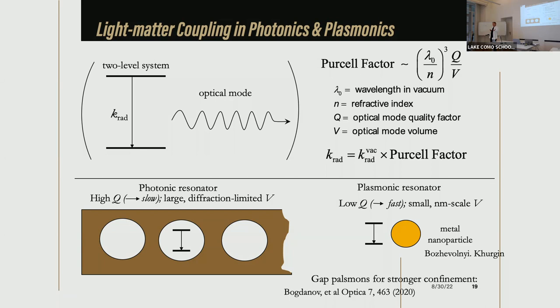But that's also why photons are robust. They don't couple to each other, they don't have charges, they don't couple much to matter. But you would like actually, when it's needed, to couple them strongly. If you would like to generate photons, to control them, you would like to have a strong coupling on demand. How to increase this coupling? You just make your photons bounce many times between two mirrors so that effectively it couples stronger, because it just goes through this atom many times. And the enhancement goes as the ratio, which is quite intuitive, of the quality factor of your cavity and inversely proportional to the volume where your electromagnetic mode is confined.